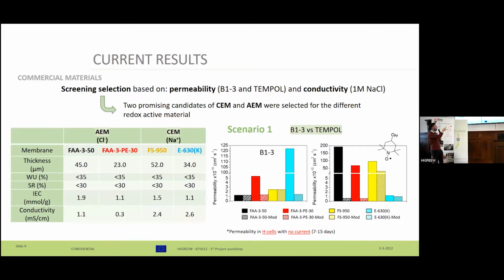Here you have in the left of the slide in this table, and I collected some relevant data of these materials, such as the water uptake, swelling ratio, and ion exchange capacity, which are found values in a typical range of battery operational mode. And as well, we checked the ion conductivity, the cationic ones being more conductive than the anionic ones.